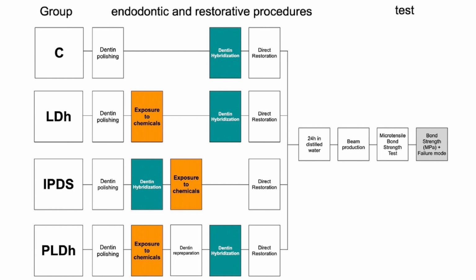After 24 hours of immersion in distilled water, a precision cutting machine was used to obtain 1 mm thick beams, and using an instrument machine, the forces at fracture were recorded in newtons. The failure mode of each beam was determined under a stereoscopic microscope and classified as an adhesive failure or cohesive failure. Adhesive failure if the fracture was between the adhesive layer and dentin, or if the fracture occurred between the flowable resin coating and restoration, and cohesive failure if the fracture occurred exclusively within the resin composite or the dentin.